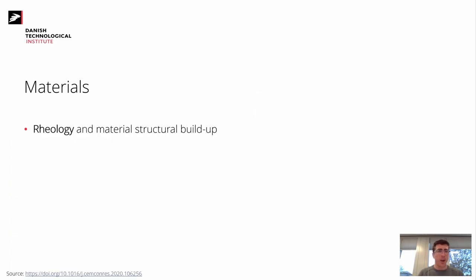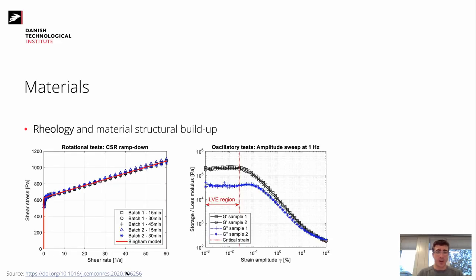So the first part relates to rheology. In these two charts, on the left side, it's a rotational test that measures basically the viscosity of the material. I have the initial yield stress as the point where the red curve is hitting the vertical axis, and then the slope of the curve will dictate the material viscosity.